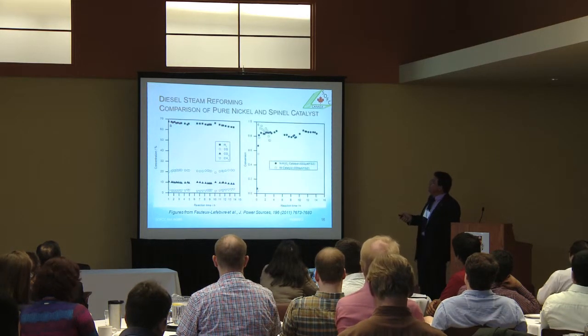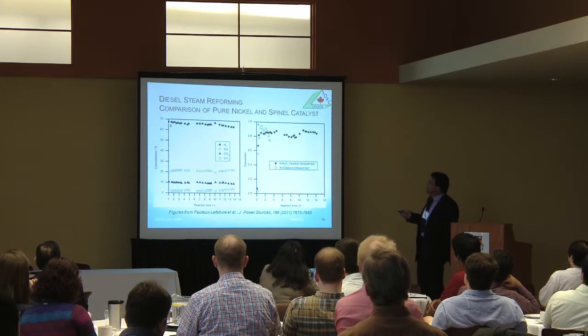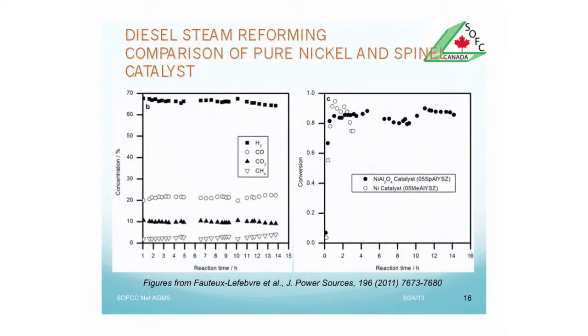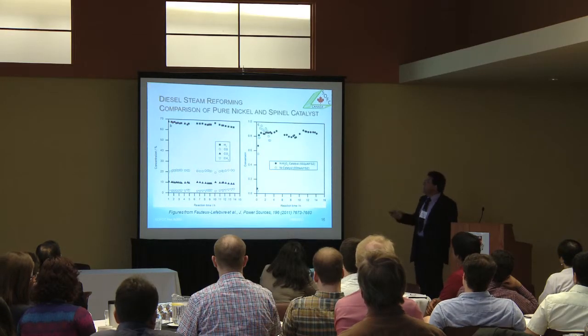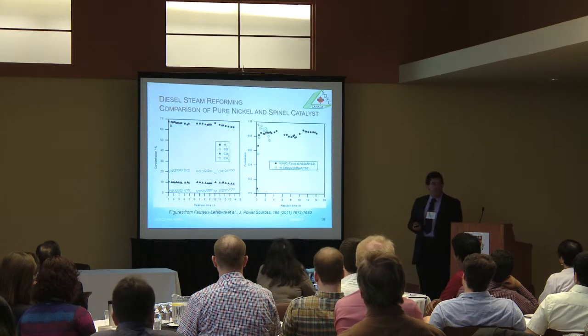So we compare what the spinel catalyst provides with a catalyst which is metallic nickel deposited on alumina and zirconia, exactly the same thing. We clearly see that the initial metallic nickel gives a very high efficiency, then it drops fast because we have formation of carbon, while the spinel catalyst is very efficient and provides a stability of about 15 hours.